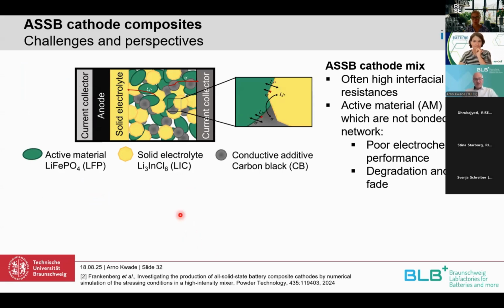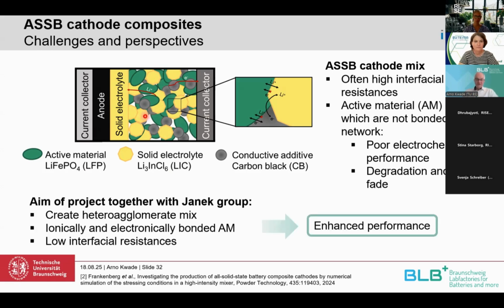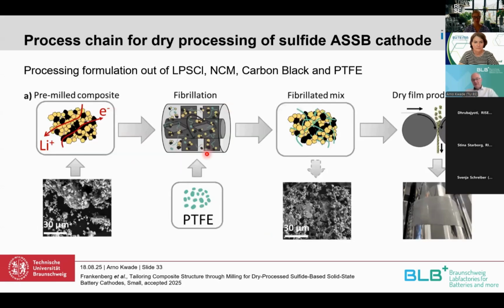And we had a nice project where we looked at the mixing of these different components, the active material, the solid electrolyte, and the conductive additives, and how we can get a good mixture and then a good microstructure within the cathode. We do it together with the Janek group, which is looking more at the electrochemistry and the microstructure, and we at the processing. And one of the recent results was just published in Small by Finn Frankenberg, or it will be in a few days, it's at least accepted.